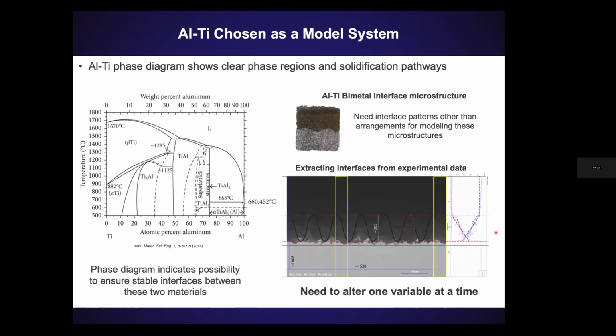In fact, the first thing we needed to do is pick something that we could do in the lab, some materials that were easily available. So we decided to go with the aluminum titanium phase diagram, aluminum titanium as our model materials. The nice thing is the phase diagram was also pretty useful to us in the sense that there were spaces where we knew that we could form Ti-Al3 between the materials at temperatures that were accessible to us using the furnace we already had in our laboratory without buying new equipment. So we knew, okay, we could probably form a stable interface between these two materials.